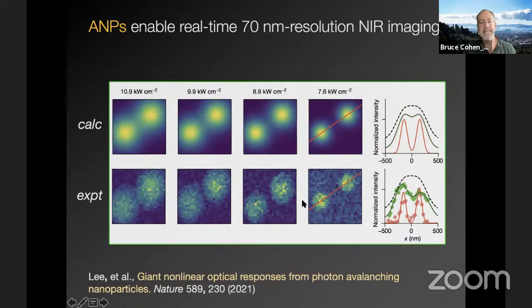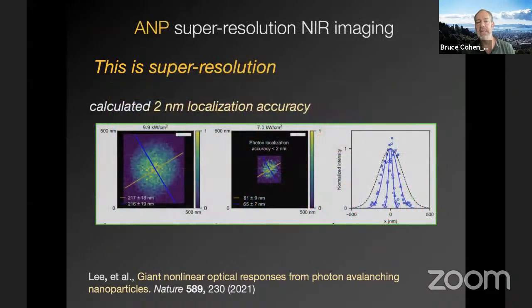And yes, this is to remind me to say this is not super resolution. This is actually at resolution. We're not better than that. But you can actually do super resolution with these nanoparticles using the sorts of point spread functions, so Fiona type things, where you get a localization accuracy, where you count every photon and you have a map and you get a geometric mean of where the photons are. And that gives us a localization accuracy of about 2 nanometers, which, these are 20 nanometer nanoparticles, so that's somewhere in the middle of that nanoparticle.